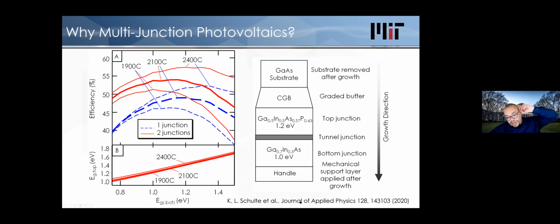This is just, we have a paper in Journal of Applied Physics. I'll skip through this pretty quickly because one question that often comes up is, well, why not keep it simple and just go single junction? In short, because we get a significant boost in performance from a second junction. So we're going with dual junction. This shows you, for a choice of first band gap material, if you change the bottom band gap material over this range, how the efficiency would change for different temperature ranges. Our nominal temperature is about 2150 C.